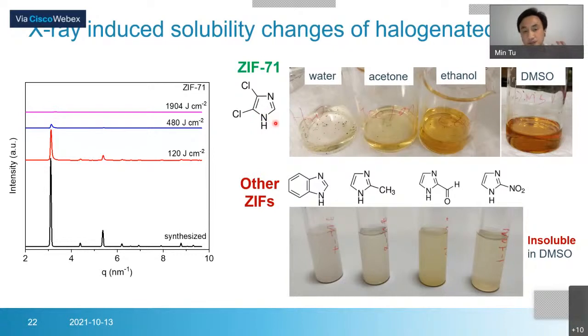And one very interesting property is, after irradiation of ZIF-71, we found this MOF is soluble in DMSO and partially soluble, for example, in ethanol, acetone, or water. But the MOF itself is not soluble in any of these typical solvents. And we also found other ZIFs, for example benzimidazole or methylimidazole. This kind of MOF with this linker, after irradiation, is not soluble in DMSO. So this is very exciting news for us, because we see the X-ray can induce damage of this MOF, and it can be soluble in DMSO.